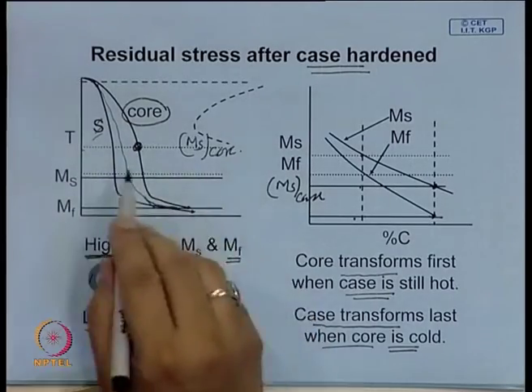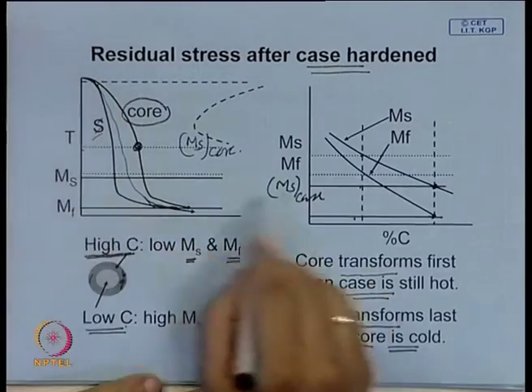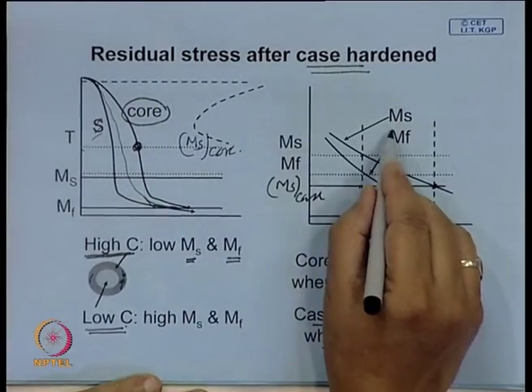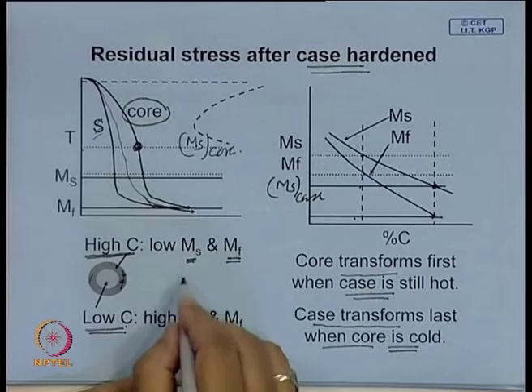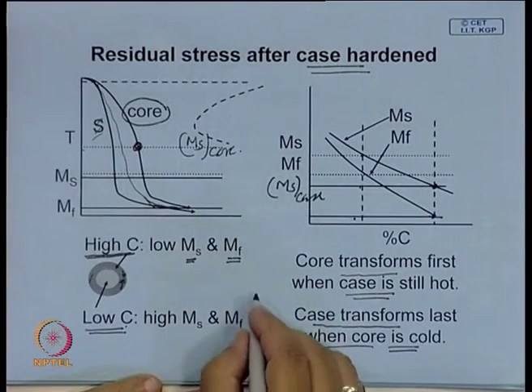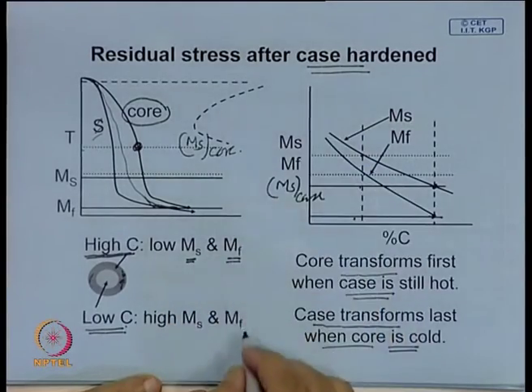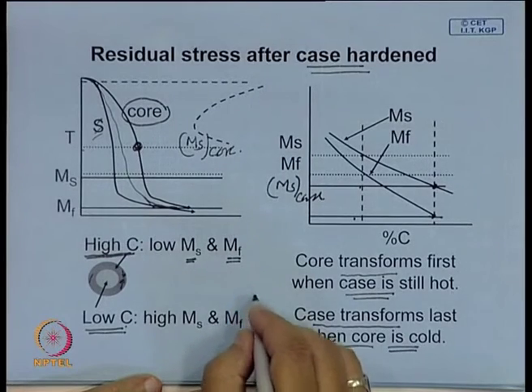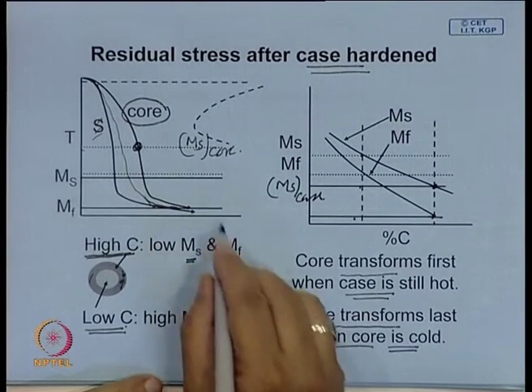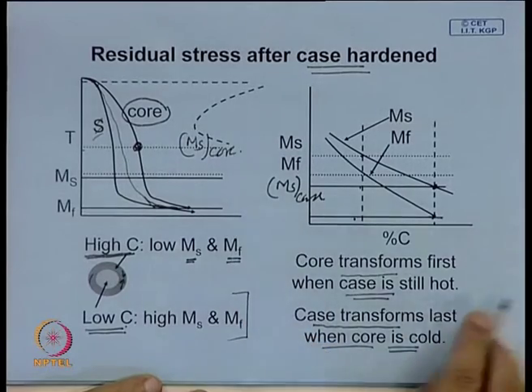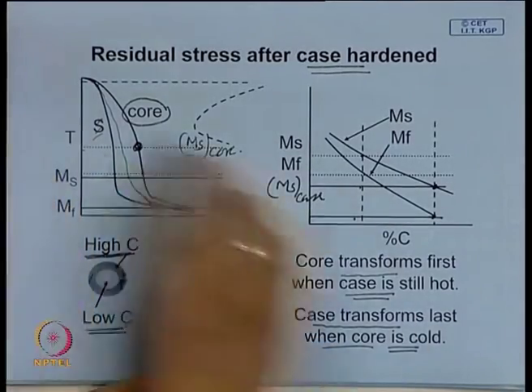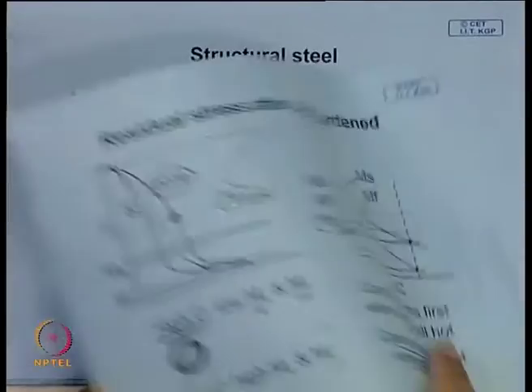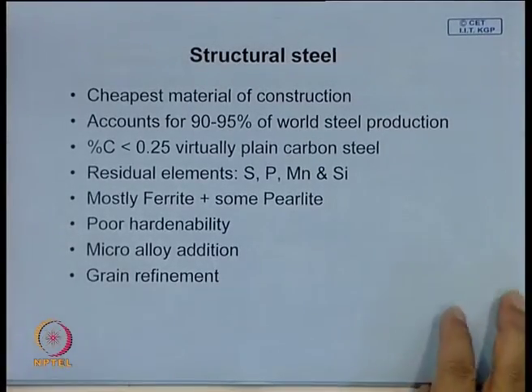So this is the reason why, because of this difference in Ms temperature, by modifying the composition, it is possible to introduce by case hardening a favorable residual stress, that is compressive residual stress at the surface, and by that you improve the performance of this component. And the same concept, these basic principles, have been used in the case of structural steel as well, and we will see how this is done.